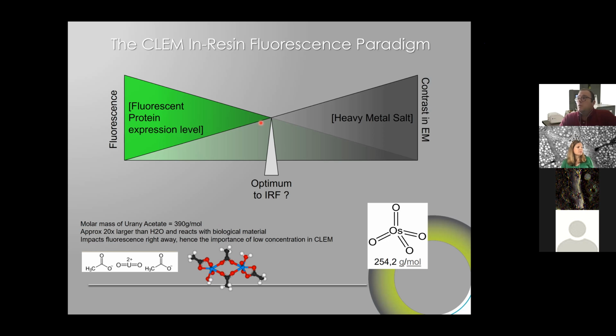So we could see it as there is an optimum in resin fluorescence where we have a very low amount of UA and a preserved fluorescence. But the problem is this balance is not optimal for both. So basically you will not have a very good fluorescence and you will not have a very good contrast. And this is especially problematic for volume electron microscopy, where currently one of the major views is that we need to have a very high amount of contrasting agent to evacuate the charges in scanning electron microscopy approaches.